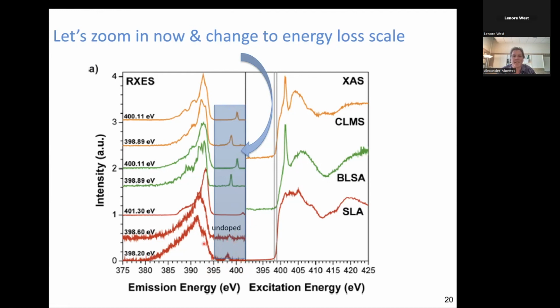What that means is we take each of these spectra and subtract the excitation energy from it. The excitation energy, of course, which is the elastic peak, the incoming energy, ends up at 0. Why? Because we just subtract the incoming energy. So these peaks here, the elastic peaks, the incoming energy, end up at 0. And then we have the energy loss scale. This is what you do when you are after energy loss features.